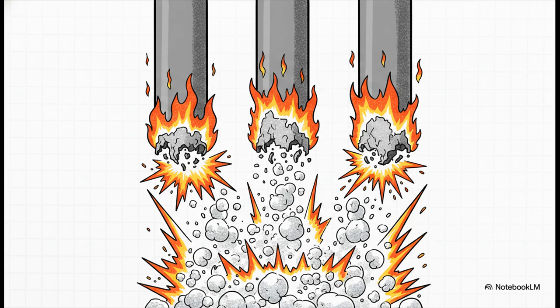Remember all that oxygen we just violently ripped away? Well, it has to go somewhere. It forms at the positive carbon electrodes up top. And at these extreme temperatures, the oxygen aggressively reacts with the carbon anodes, forming carbon dioxide. The sheer violence of this chemical reaction generates its own massive heat, meaning these cells are actually self-heating. But it also means those massive, incredibly expensive carbon electrodes literally burn away during the process and have to be continuously replaced. It's a violent, exhausting chemical loop for sure.